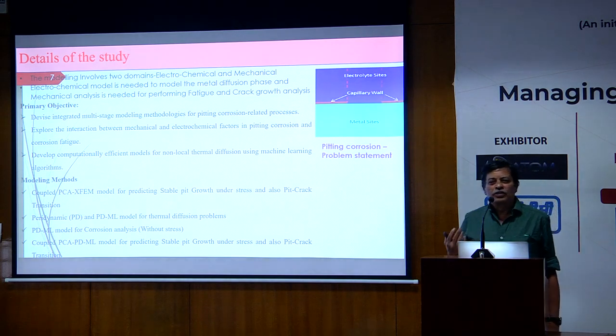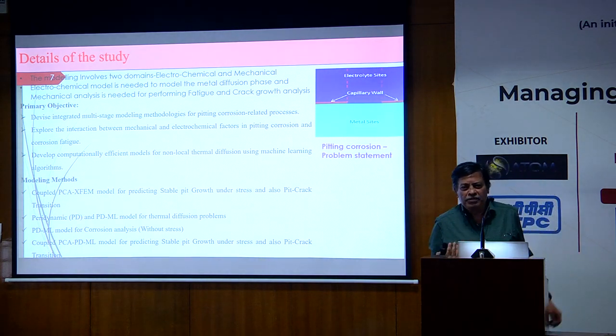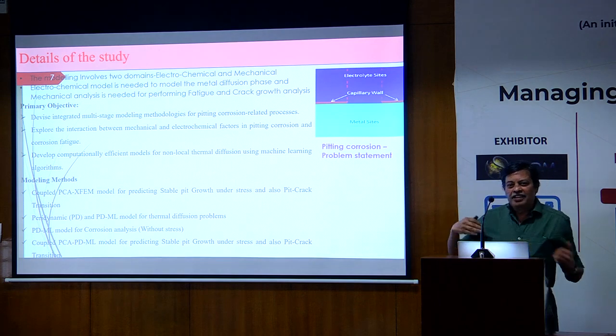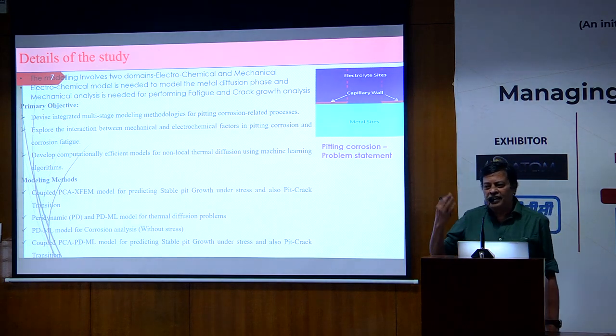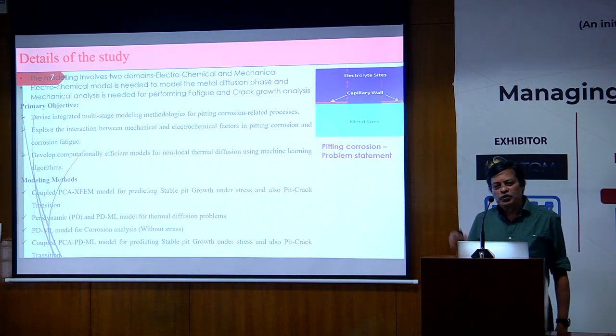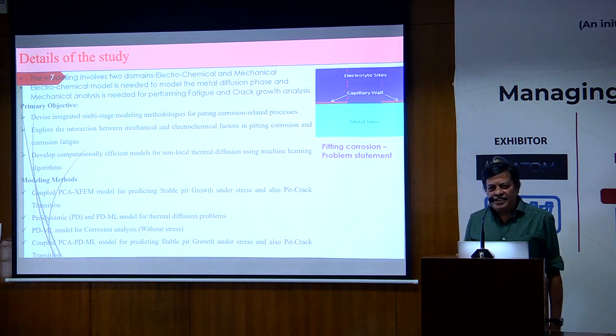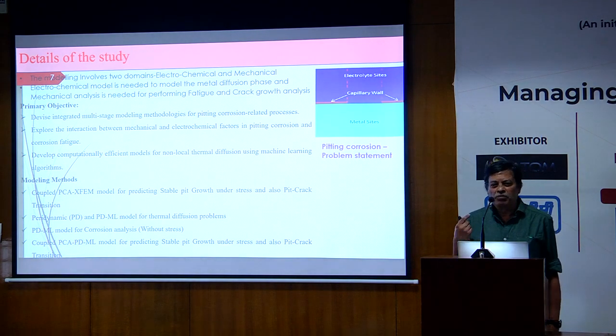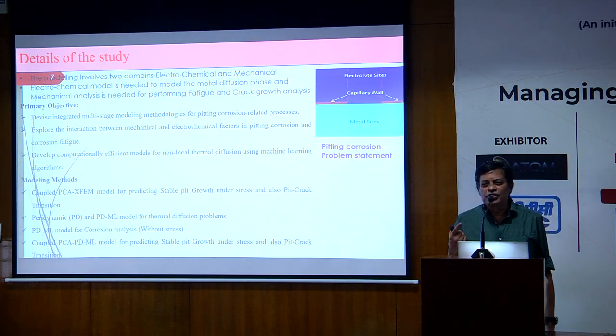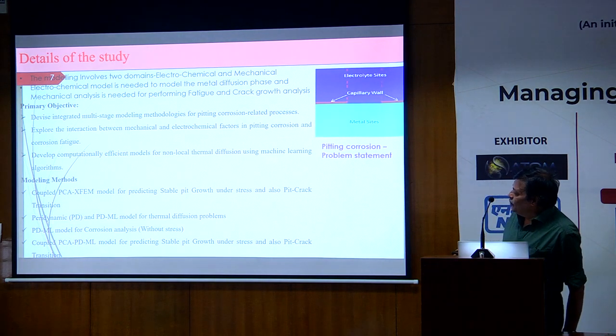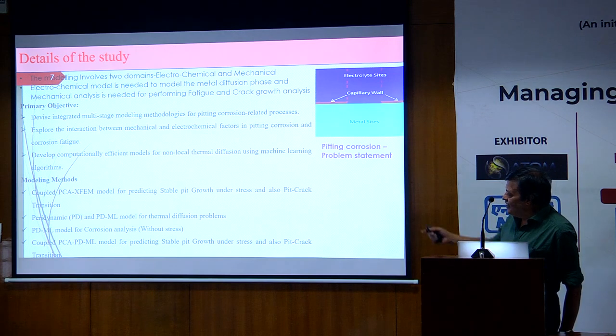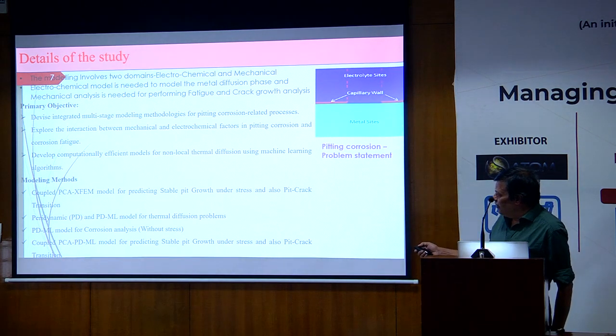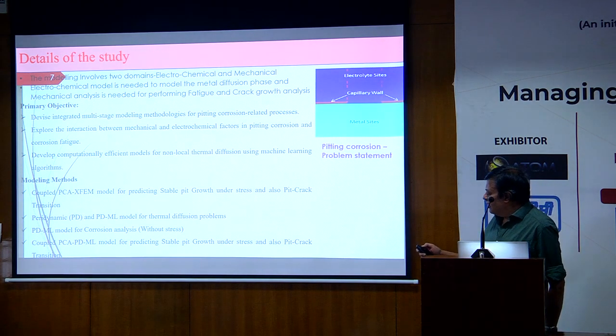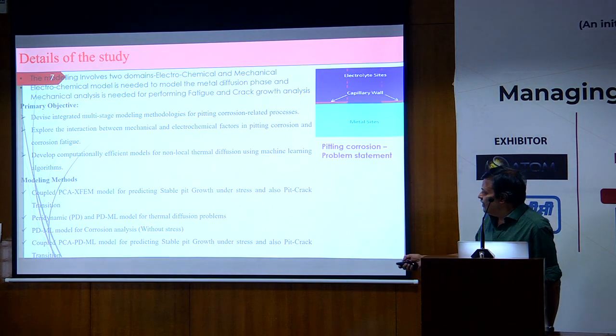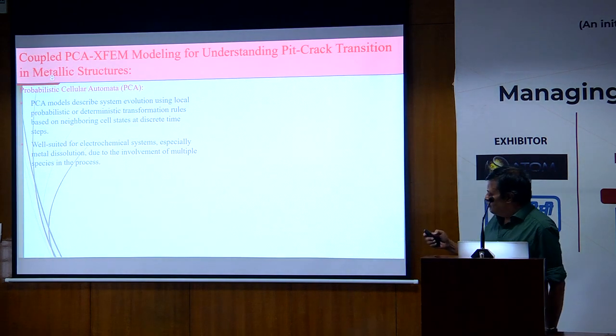So we need to track this. If you use a conventional FEM type, the mesh has to be refined every time the pit happens. So instead of doing that, we used extended FEM with an enrichment function so that this enrichment can be modeled only once. So essentially what we have done is, we have done a number of different models. What he talked about is only the PCA model.